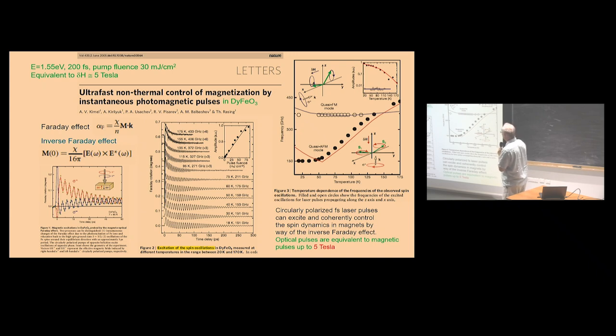At high temperatures, there is an antiferromagnetic order. The spins are antiparallelly ordered along the x-axis, but there is some tilting angle due to the Dzyaloshinskii-Moriya interaction. And then you can excite this quasi-antiferromagnetic mode, quasi-ferromagnetic mode, if you have a beam along the x-axis and you produce magnetization along that axis. There is a weak ferromagnetic moment. So they can observe such magnons versus temperature.